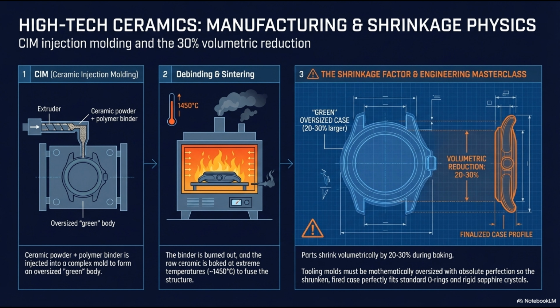If ceramic is so hard that it destroys standard cutting tools, how do we actually shape a watch case out of it? Let's review high-tech ceramics, manufacturing and shrinkage physics. We are looking at CIM injection molding and the terrifying reality of 30% volumetric reduction. Look at the three-step diagram on the screen. Step 1 is CIM, or ceramic injection molding. We do not cut a block of ceramic. We take raw, microscopic ceramic powder, mix it with a polymer plastic binder, and melt it. An extruder injects the slurry into a complex steel mold to form an oversized, fragile green body case.